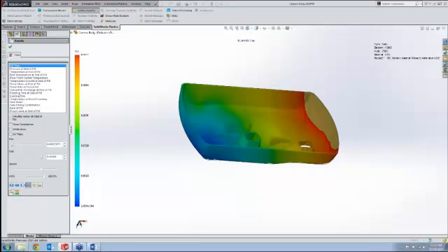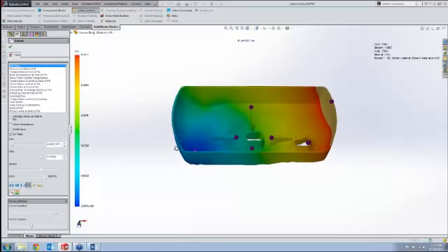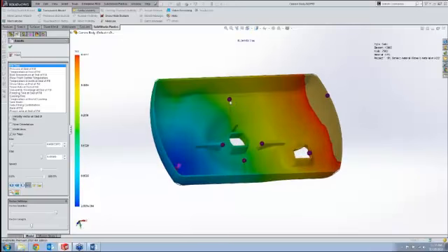The other thing to note here is some of the check boxes in this case. So if I take a look at air trapping inside of the mold here, I turn that on. The purple spheres that have now showed up on the screen here are showing potential places where you would want to vent the mold. All the ribs have an air trap as plastic is flowing up into those. As the plastic flows around this area, we have an air trap. And then we get this because it's the last place to fill inside of the animation itself. And you can kind of see where the plastic's flowing, get an idea of these. But the purple spheres just give you a good, clear understanding of where gases may be trapped in the mold relative to the injection process.